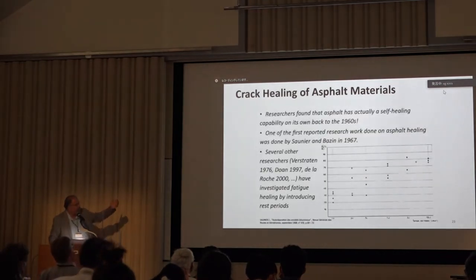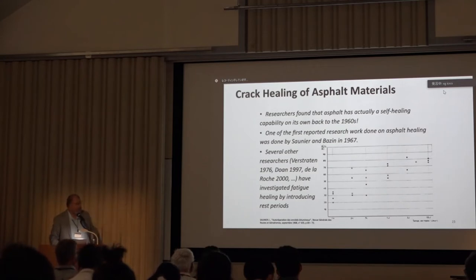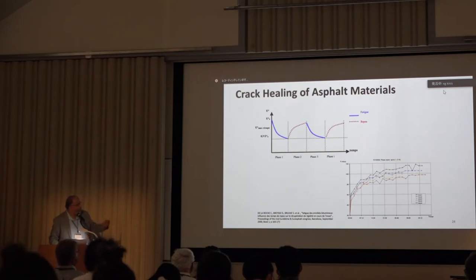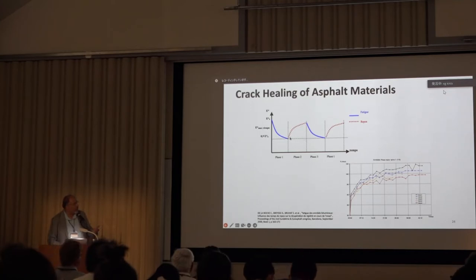Again, older research continues later, with Bazin and Saunier, 1967, and other people continued. Chantal de la Roche from IFSTTAR worked on healing in 2000, and this is some of her work, where we can see a fatigue test. You can see here that the modulus drops, and during phase two, which is a rest period, the modulus will increase again. And then we restart the loading and the modulus, or the stiffness, drops, okay? The blue curves are loading curves, and the red curves are rest periods, and the property that we were considering here is the modulus. This is from De La Roche and the other researchers from France.